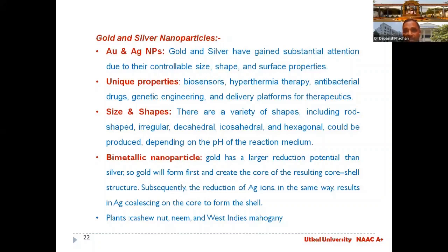and the nanoparticles are achieved by employing plants as biological factories via green chemistry based techniques. In the study of nanoparticle synthesis, they also discovered that a variety of shapes, including rod shape, irregular, icosahedral and hexagonal, could be produced depending on the pH of the reaction medium. Furthermore, a leaf extract of Eucalyptus macrocarpa could be used to synthesize gold nanoparticles. The results from this study show that spherical particles with a size ranging from 20 to 80 nm were obtained as the main product.